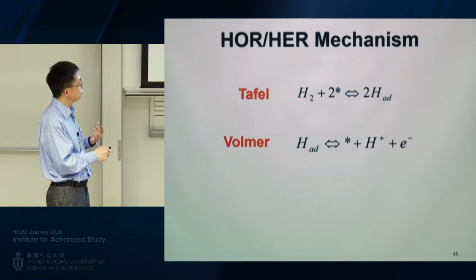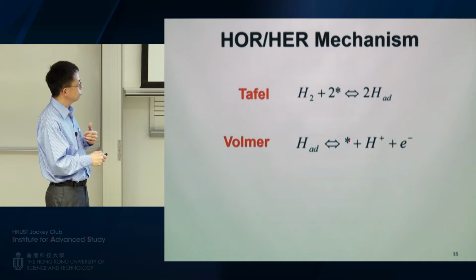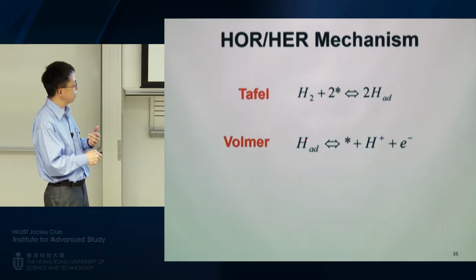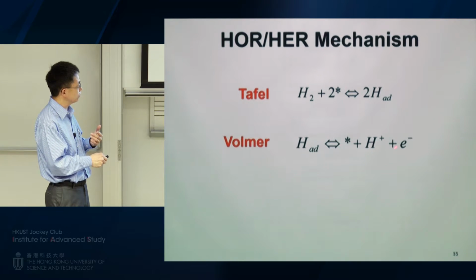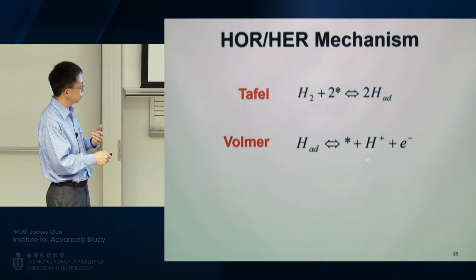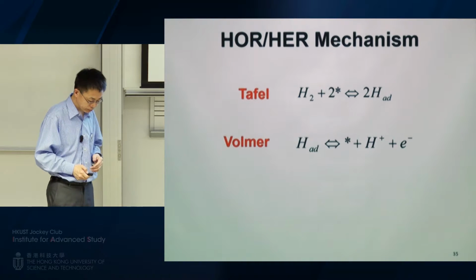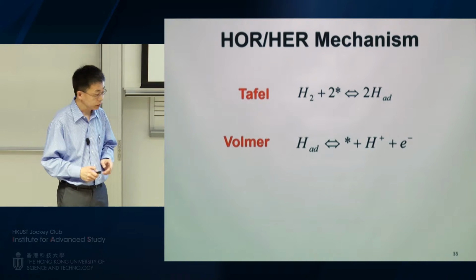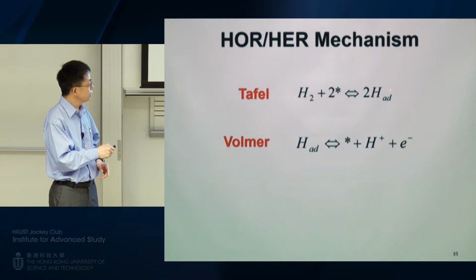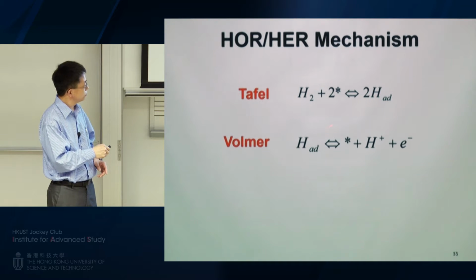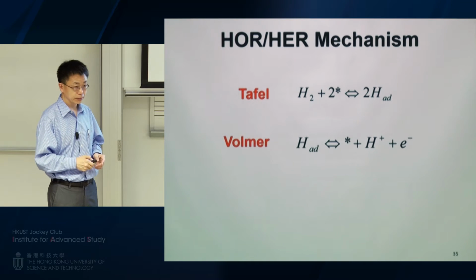So you have this hydrogen molecule coming in, split into two atoms. One atom will get onto a site, so you become hydrogen adsorbed. And then you have this Volmer step, which is the real oxidation step. So you have this one get oxidized to give up an electron, become a proton, give back the site. So these are the two steps. The point I want to make here is, if you take a closer look, hydrogen adsorbed is the key intermediate.